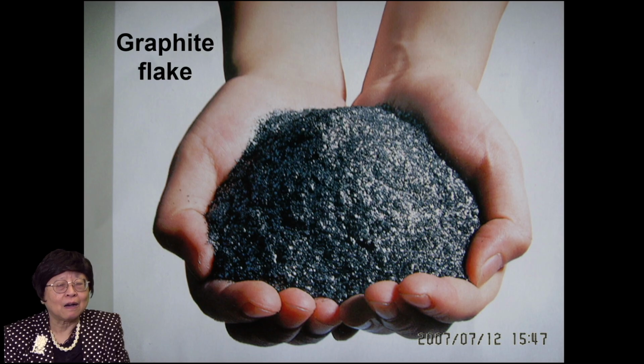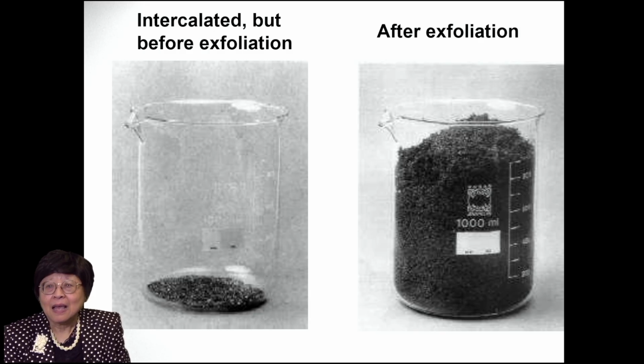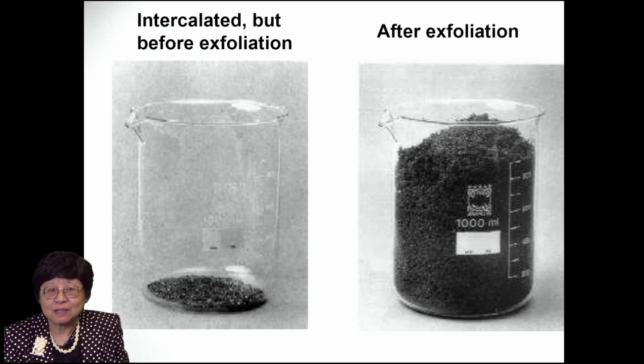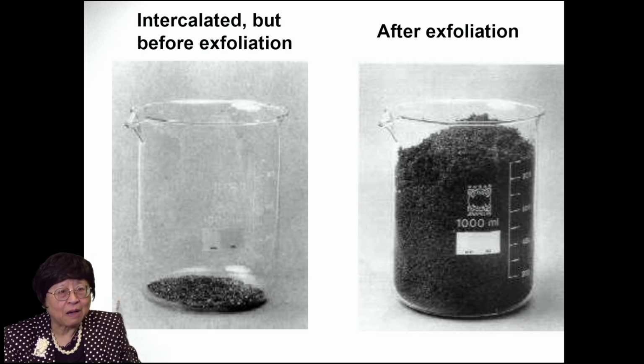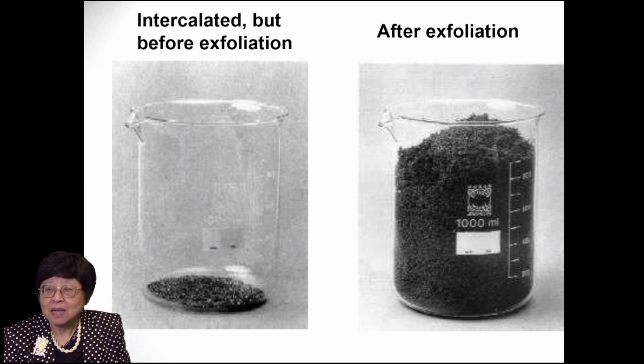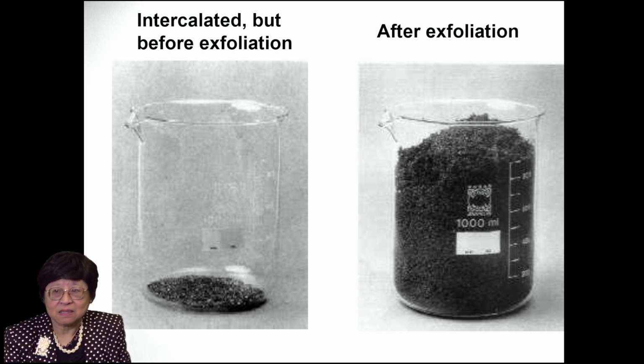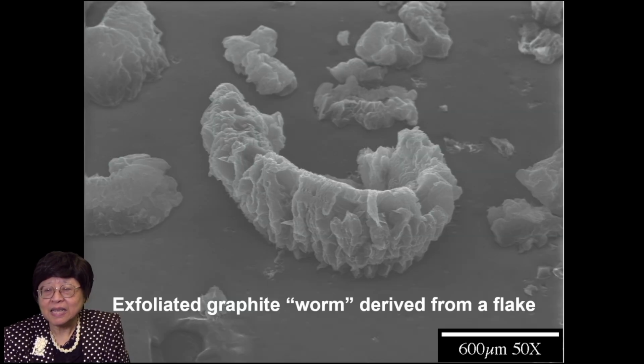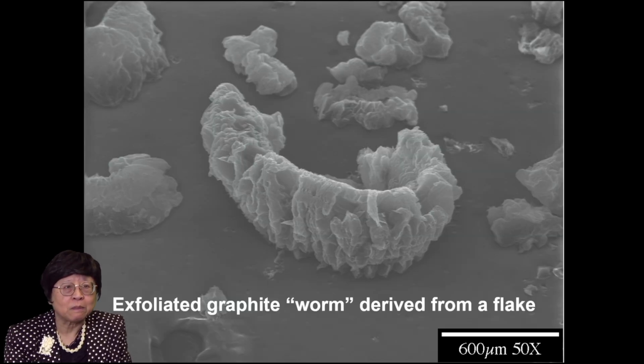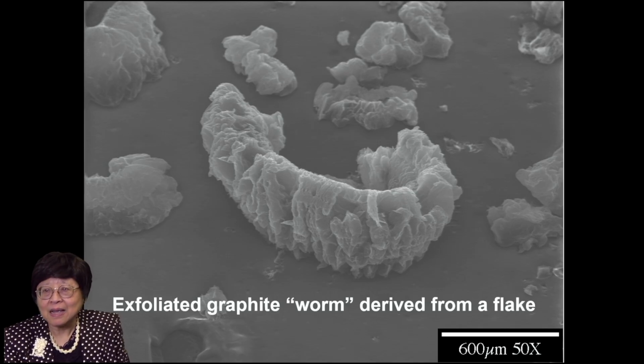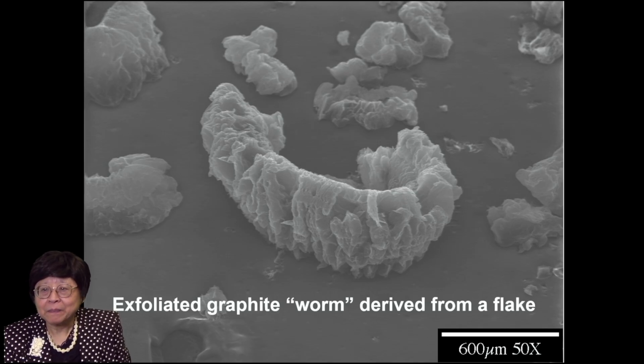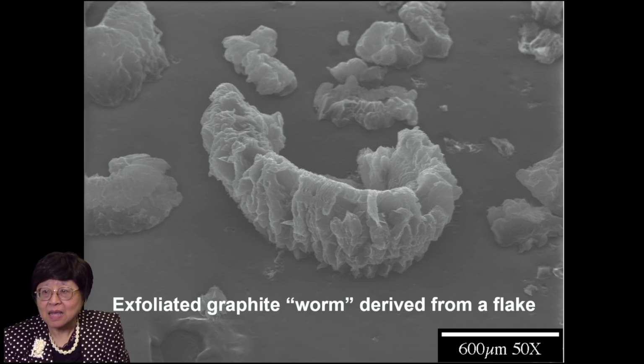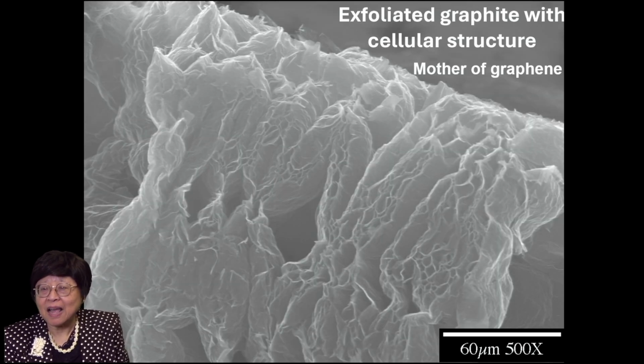Another direction of exploiting a high surface area is to use graphite flakes. One can intercalate the graphite flakes to make that sandwich compound, and then rapidly heat it, and it would puff up, like popcorn, and we call that exfoliated graphite, as shown on the right. And each piece of exfoliated graphite emanating from a flake looks like a worm, and it has a cellular structure. Okay, and this shows a higher mag view of this cellular structure, a part of a worm.